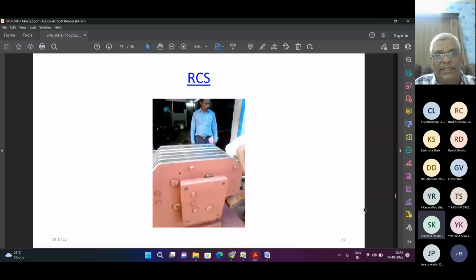This is the RCS. I would have shown a beautiful image of the HPT RCS process. You can see this is a very useful machine where only the length of the sample should be high, whether it is a 10 mm by 10 mm by 500 mm length sample, and you can do 10 mm, 8 mm, 6 mm, 4 mm, any type of sample you can bring. You can do it in one machine itself.